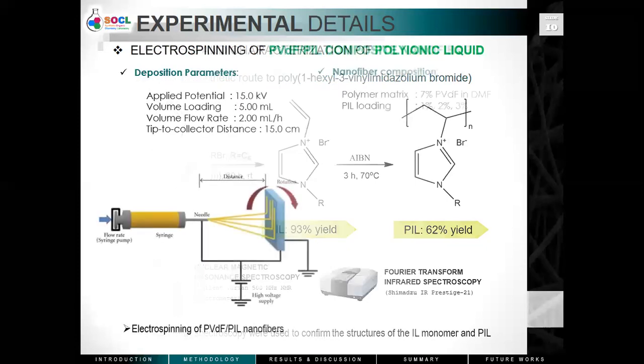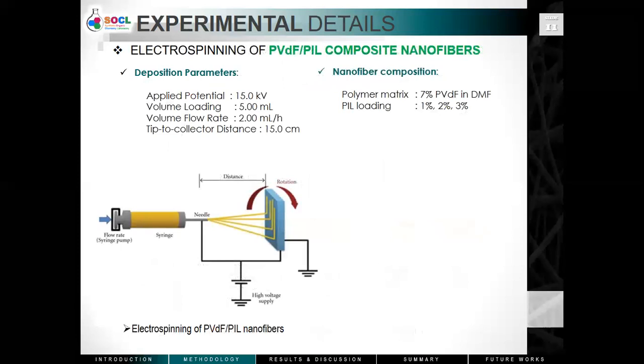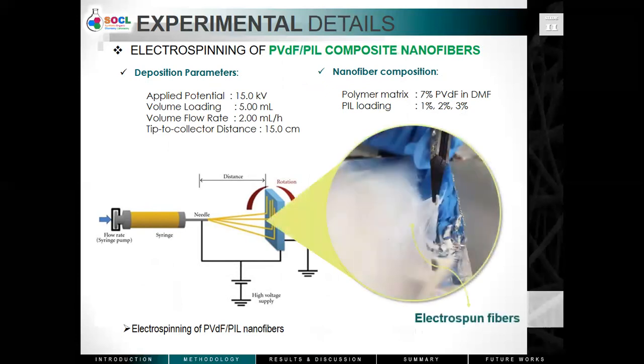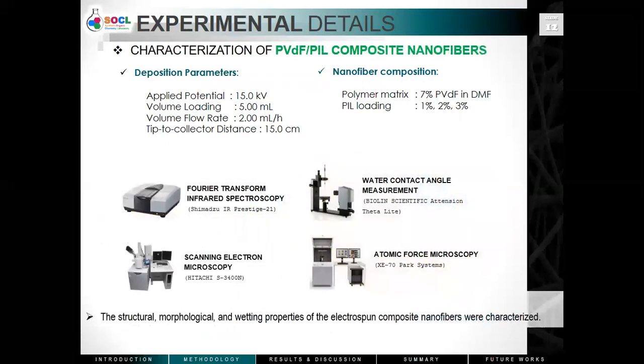For the electrospinning of the composite fibers, polymer solutions of 7% PVDF mixed with a varying PIL concentration in dimethylformamide were prepared. A 5 ml sample for each solution was electrospun using these deposition parameters. And the electrospun nanofibers were then characterized using available techniques.